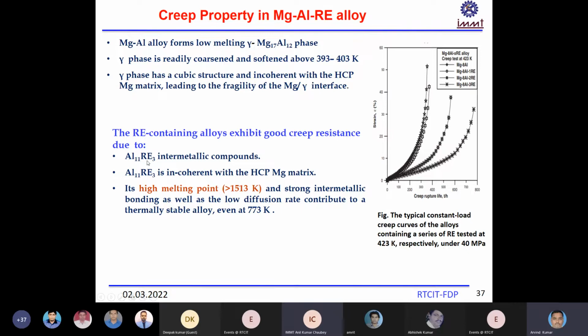So these problems are addressed by using rare earth elements. Rare earth elements are more reactive with aluminium compared to magnesium. So in the magnesium aluminum rare earth alloy, first intermetallic compounds form, Al11RE3, and it is incoherent with the HCP matrix, and its melting point is also high, so that it cannot melt during your operation at 300 to 400 degree temperature. So that's why it also increases the creep resistance of this alloy.